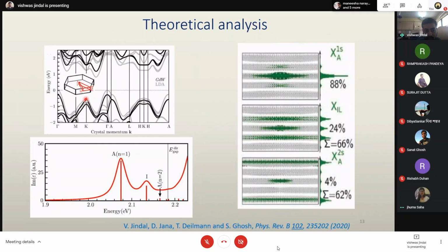When I say this is an indirect band gap material, if you shine a laser of high intensity, you won't get any emission out of it, or only a very small emission, because once the charge carriers get excited, they tend to accumulate at these points. They cannot recombine radiatively because they are separated in momentum space, and photons have a very small momentum.